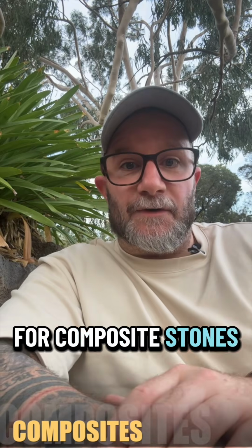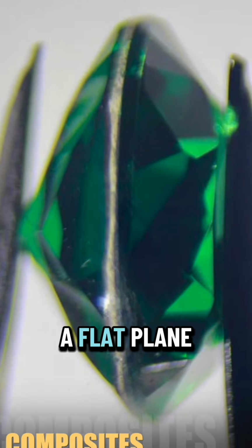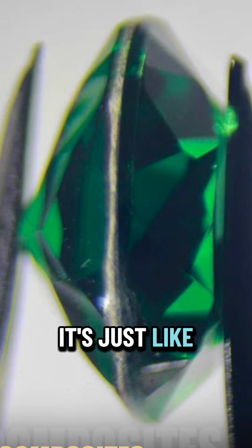Now, if you see those donuts, it's just a round bubble where the light hits the edges, creating a dark ring. And that dark ring is a classic sign of man-made glass. Also, watch out for composite stones like doublets. If you see a flat plane right through it, it's just like the glue holding two separate pieces together.